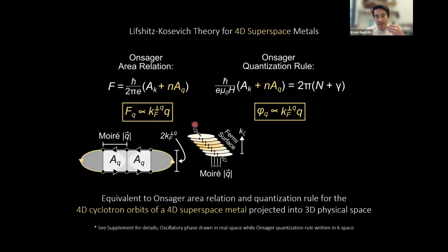And so if you were to elevate the Fermi surface, the quasi-2D or purely 3D Fermi surface, into one higher superspace dimension based on not the lattice mismatch, but the momentum mismatch of the crystal, you'll find that this pocket is replicated along the staircase in synthetic dimension. And if I project down into the physical dimension, the cyclotron orbit now looks like I have an electron that propagates in this Fermi pocket. It hops an integer multiple steps of 2, 3, 7 number of times along the Moiré superlattice, and then it completes its orbit. And this whole area includes this anomalous 4-dimensional area, which is the momentum Q times the Fermi wave vector in the orthogonal direction.